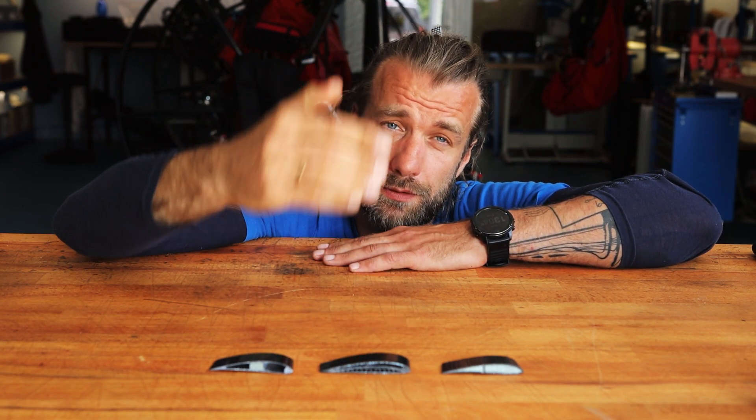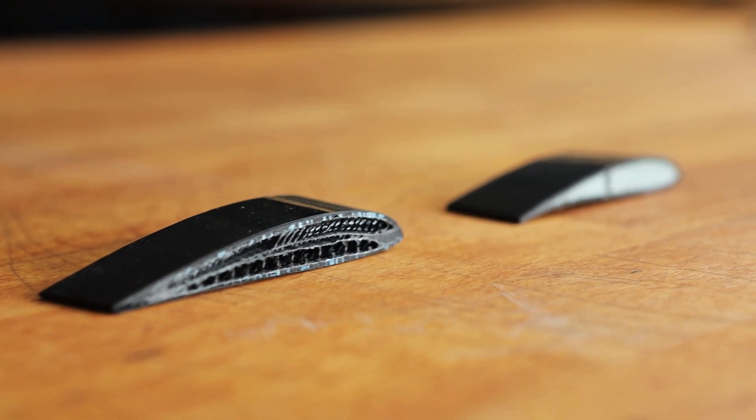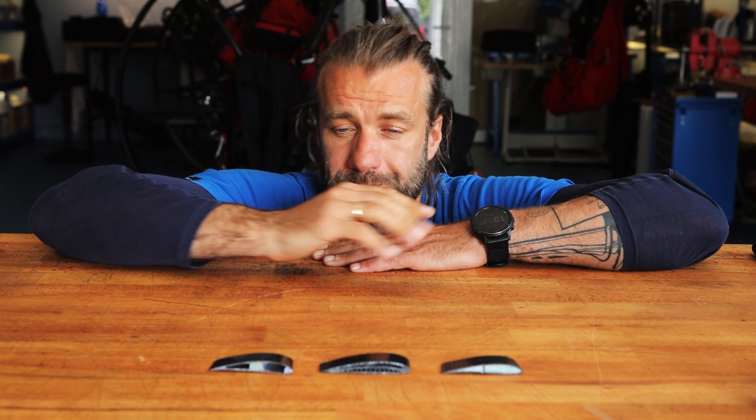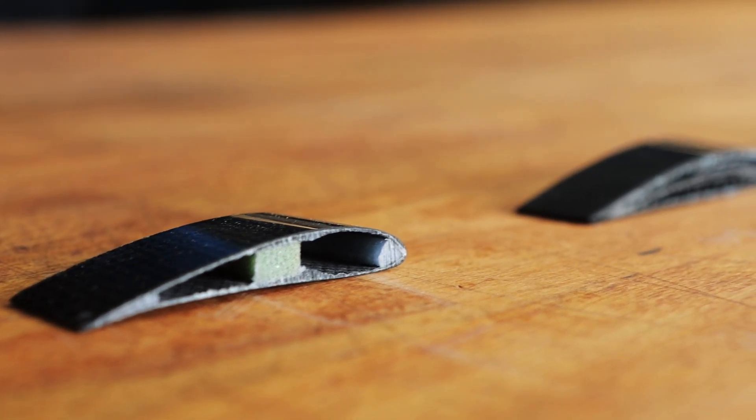This is the Helix. It's actually not carbon fiber but a very sophisticated 3D mesh fiberglass fabric, and already you can see that the leading edge has a lot more material, so they're more robust, more resistant to stones, and also easier to repair. The last one is a section of the Scout propeller, and as you can see the leading edge is filled with composite material, so as long as the stone bites into that composite material but not through it, it will be very easy to repair.